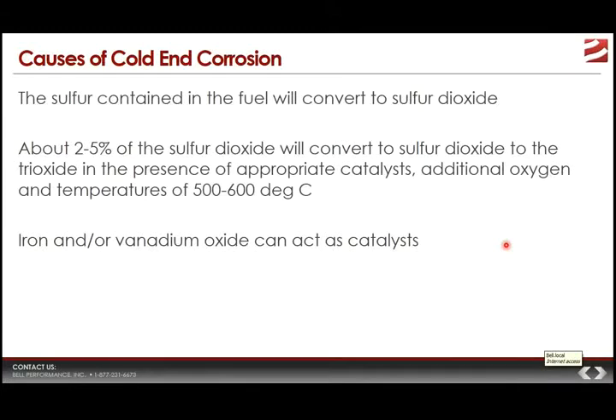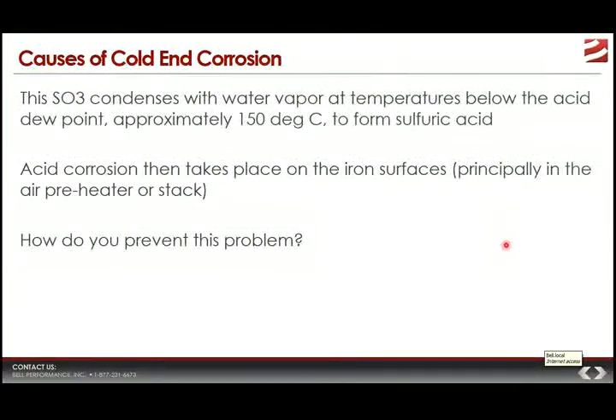However, a certain percentage of this SO2 gas will, given enough time and the right conditions, oxidize further. It'll have an additional oxygen added to it, which converts it from sulfur dioxide to sulfur trioxide. And this is a problem. How much of this conversion happens? Well, it depends on certain things. But one of the things it can depend on is the physical presence of certain catalysts like iron oxide or, very importantly, vanadium oxides.